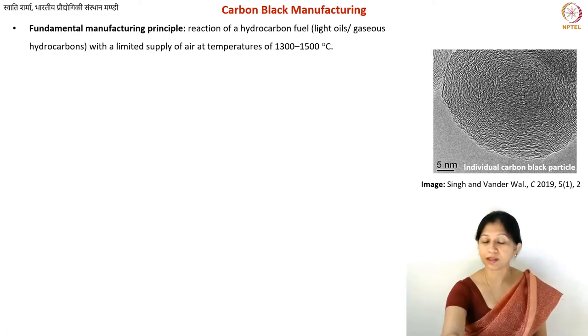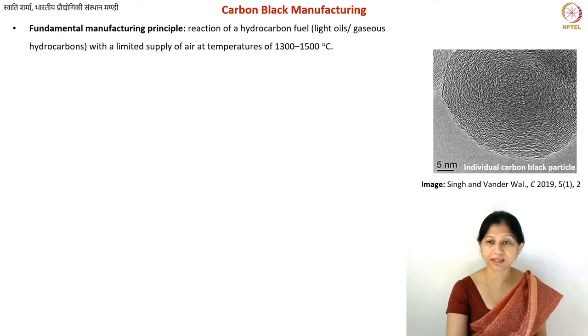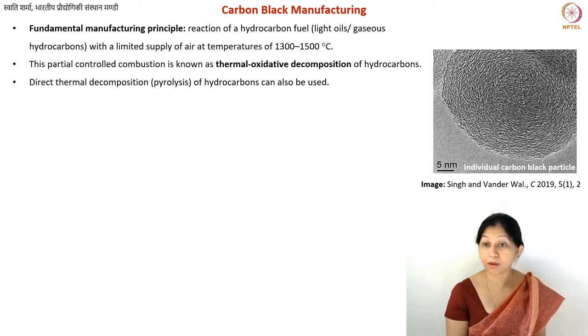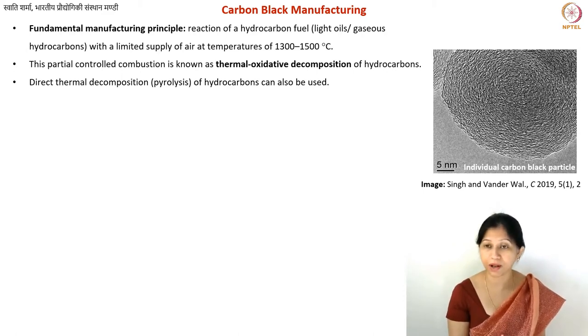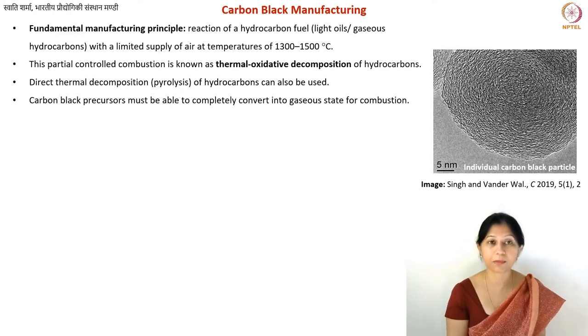The candle experiment or diffusion flame experiment, where you collect carbon smoke and filter out the particles, is also very relevant here. This is thermo-oxidative decomposition. In some cases, especially when using acetylene, you can also use pyrolytic processes — that is called thermal decomposition. But the most common technique, even industrially, is thermo-oxidative decomposition for carbon black production.